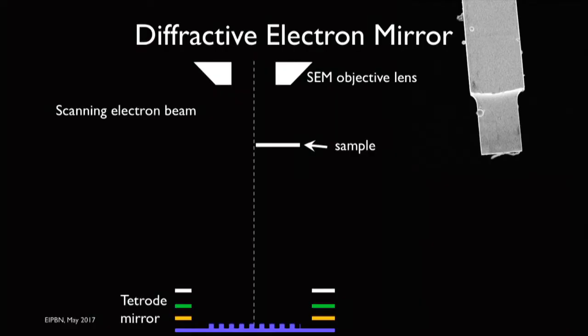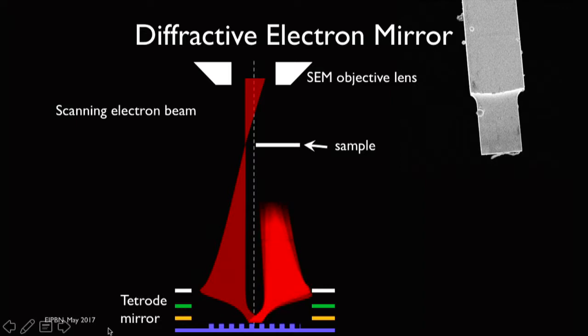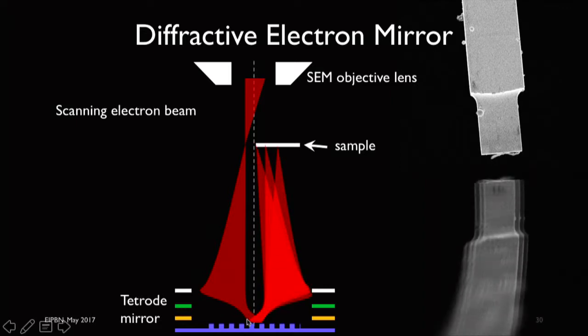So now let's go back and revisit the proof of principle experiment that I showed earlier for the flat mirror. Now let's see what happens if we replace the flat mirror with this topographical grating, or the diffractive mirror. What would happen is that the electron that comes down not only gets reflected, but it also gets diffracted. And all those diffracted beams get refocused on the sample plane again. So if we used to get one image of the bottom surface before, now we're expecting multiple images of the bottom surface, because we have multiple focused beams on the bottom surface. So this is the kind of image that we would expect to see, the one on the bottom right.